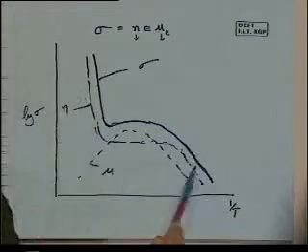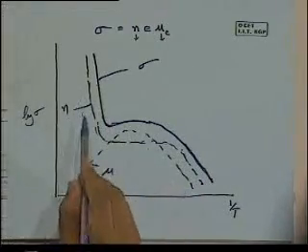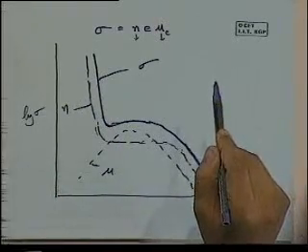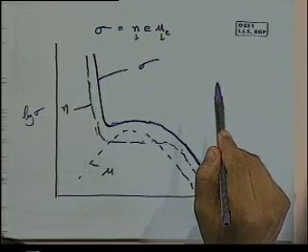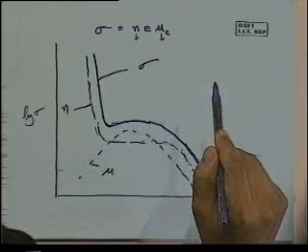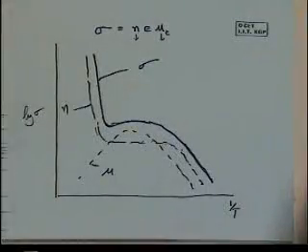If you had to draw this for a metal, conductivity would decrease with increasing temperature. There is no additional generation of carriers in a metal, but there is an increase in scattering — the mobility term dominates. The number of electrons remains roughly constant, but mobility is decreasing significantly due to increased scattering, giving a decrease in conductivity for a metal.